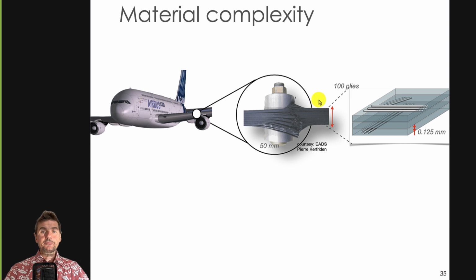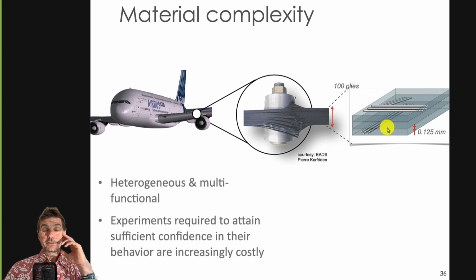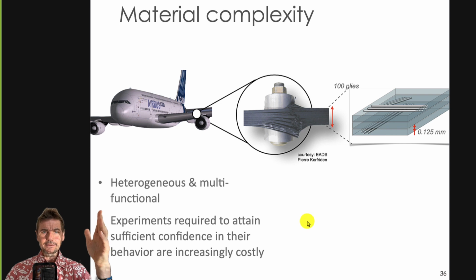For example, here you have a bolted joint: 50 millimeter bolted joint, 100 plies, 125 microns per ply, with nanoscopic fibers. This is a heterogeneous multifunctional material, and you need a certain number of experiments, similar to Paris law, to be confident that the coefficients of Paris law that everybody uses, C and M, are correct.